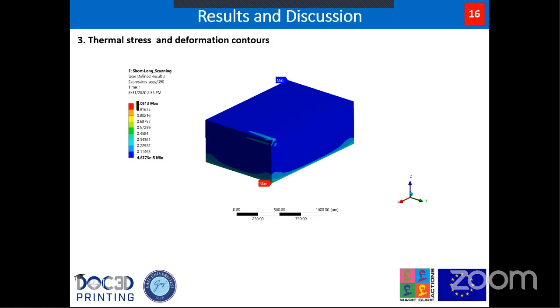A stress above 1 means that yield happened. That means there are cracks, there is a defect in the part, and any values below 1 mean no problem. So in this part we exceeded 1, so we have cracks in this part, and defects will happen during printing. So how to solve this problem?